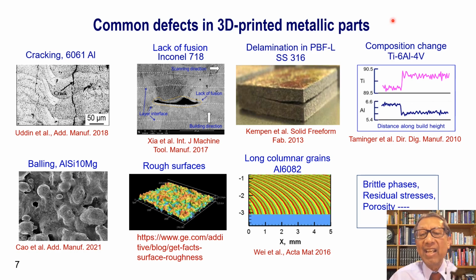Defects are very common in additive manufacturing. For example, there can be cracking, lack of fusion, residual stress and distortion, and in extreme cases, parts can be separated from the base plate, so there can be delamination, and also many of the alloys contain volatile components, and at high temperature they can be selectively vaporized so that the composition of the final part may be different from the composition of the initial feedstock. In this case, we are showing printing of a titanium 6 aluminum 4 vanadium part in which aluminum has been selectively vaporized so that its composition is much lower than that in the feedstock material.